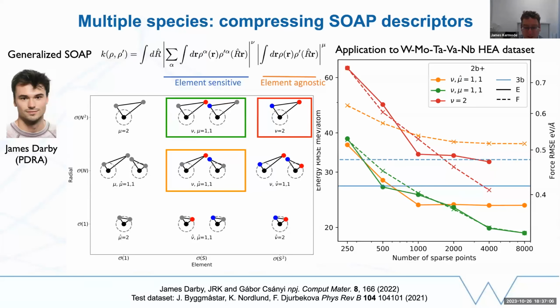We tried this out for a challenging database containing 5 different metal atoms as a high entropy alloy data set. 1, 2, 3, 4, 5. Yeah, that's right. And this is based on some previously published work by Jesper Byggmästar in Kai Nordlund's group, where they'd actually decided that the best approach was not to use a many-body descriptor at all, but to stick with a 2-body or 3-body descriptor, because it's very challenging without any compression to actually fit these models. And you can see that the full SOAP is saturating here at a limited accuracy. But with the compressed approaches, we can get down to higher accuracy, and we can keep improving as we increase the size of the basis set, essentially the number of sparse points that we include. This point here, you can see it stops earlier. That's actually because it's very challenging to fit these very large models,